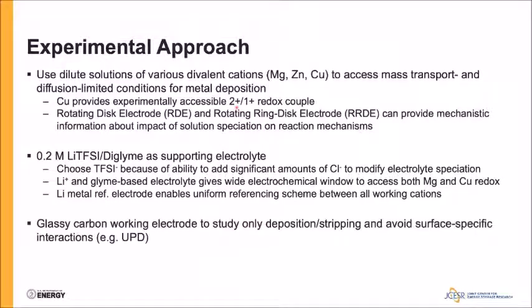And then finally, I'm going to be using a glassy carbon working electrode in all cases. The reason for this is because it allows us to rule out a lot of other surface-specific effects like UPD, surface-specific anion adsorption, and really lets us get at the fundamental deposition and stripping response.